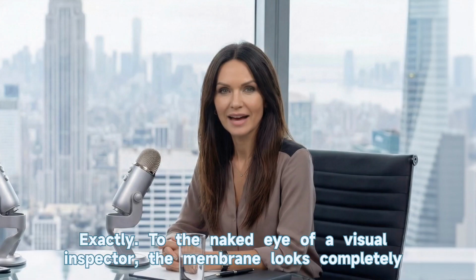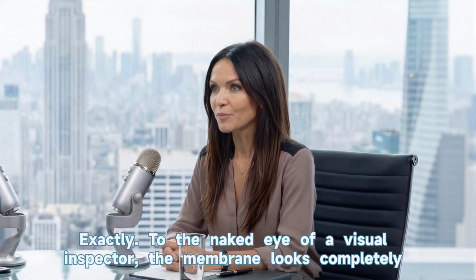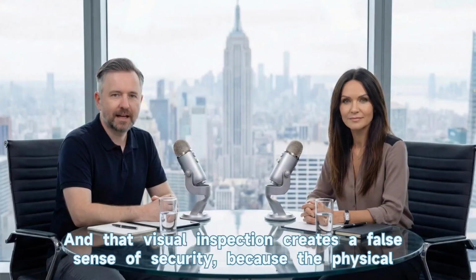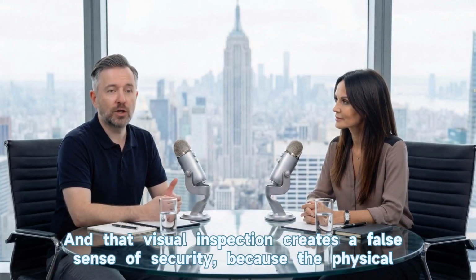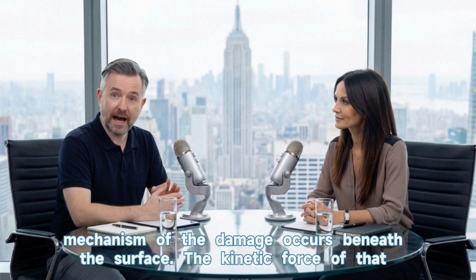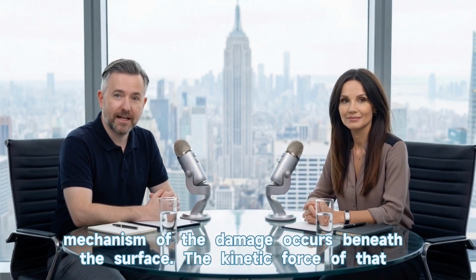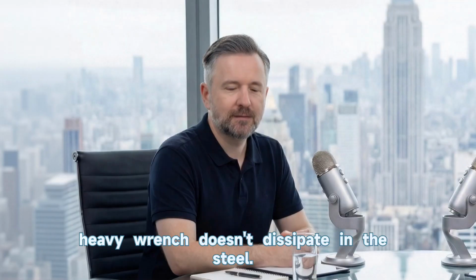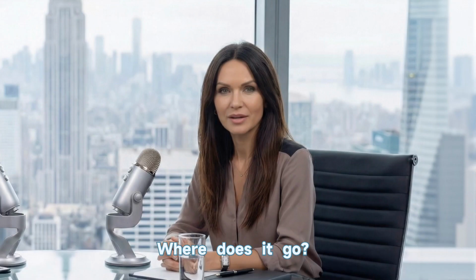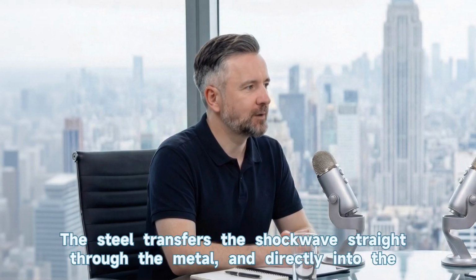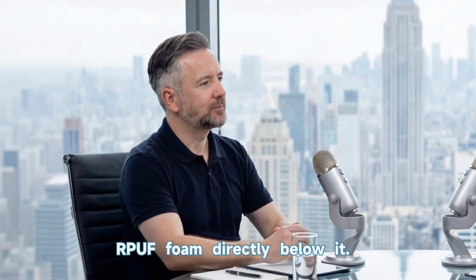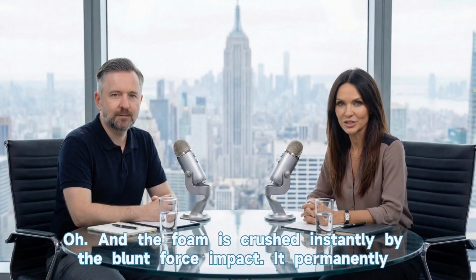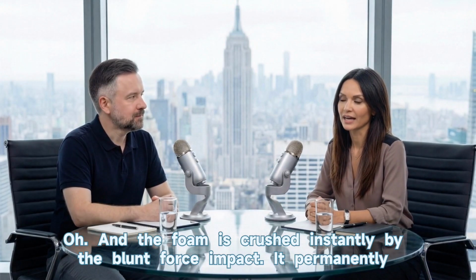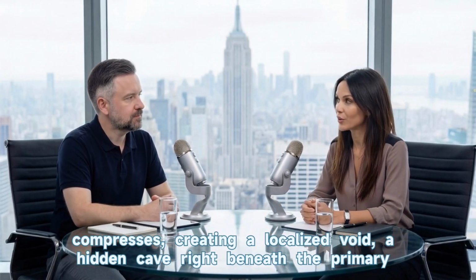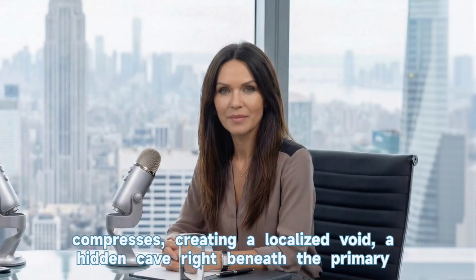Oh, it's fine. Exactly. To the naked eye of a visual inspector, the membrane looks completely intact. And that visual inspection creates a false sense of security because the physical mechanism of the damage occurs beneath the surface. The kinetic force of that heavy wrench doesn't dissipate in the steel. Where does it go? The steel transfers the shockwave straight through the metal and directly into the RPUF foam directly below it. And the foam is crushed instantly by the blunt force impact. It permanently compresses, creating a localized void, a hidden cave right beneath the primary steel.